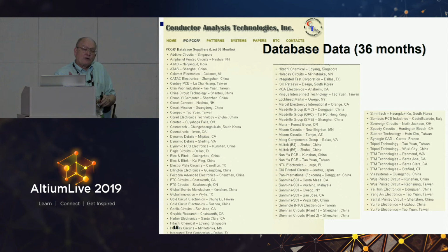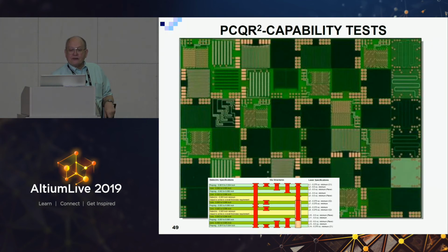Typically, McDonnell Douglas, Boeing, and Lockheed Martin require that they successfully pass this benchmarking, and they requalify every 6 months. There are coupons on the board that match this benchmark, so that every single panel that Lockheed Martin or Raytheon buys can be traced to this statistically significant benchmarking. It's a really well-designed, excellent quality reliability control system that works quite well. It works because it's built out of these 2.5 centimeter square multilayers that have all kinds of stacked vias, drilled vias, and sequentially laminated vias. And it goes up to 24 layers.